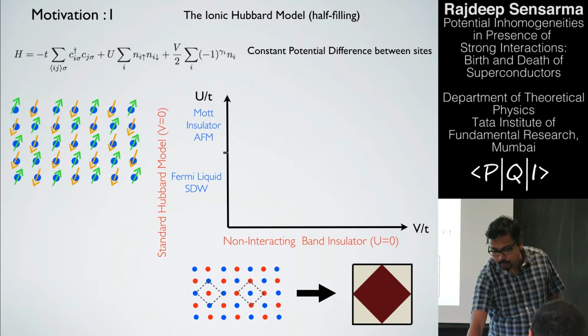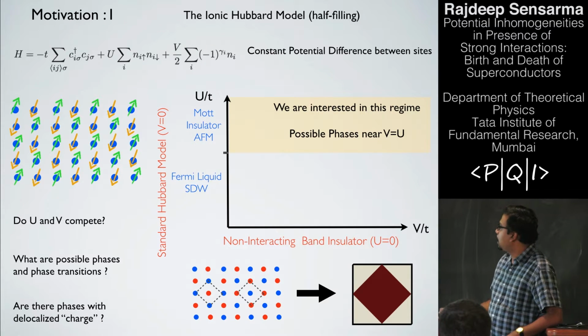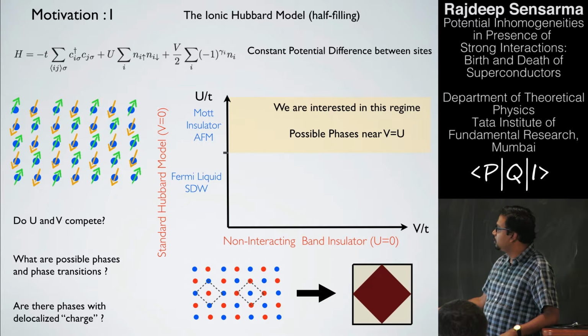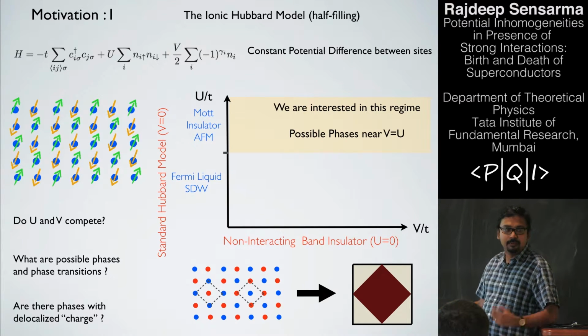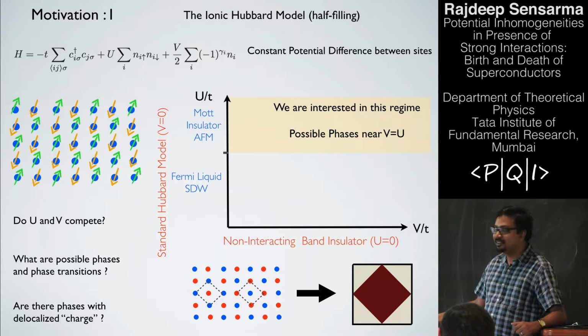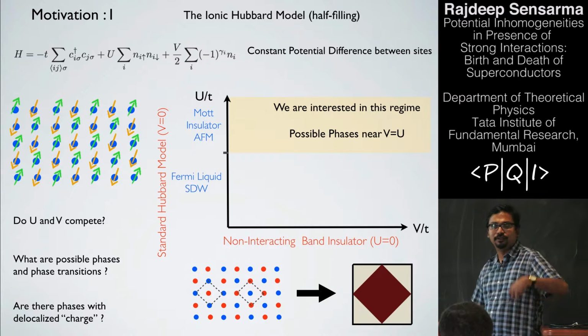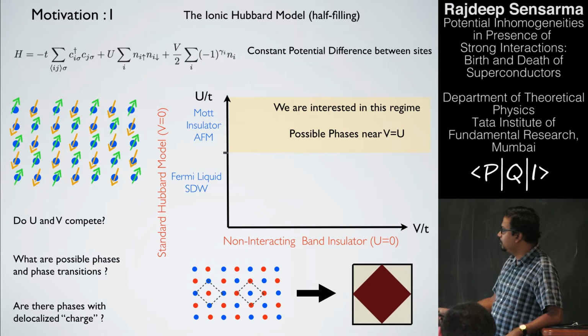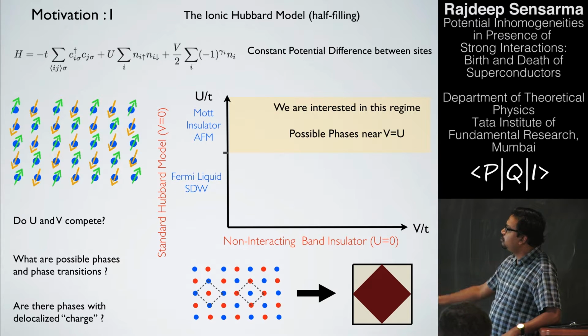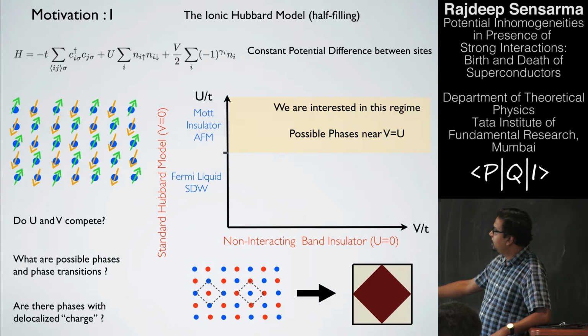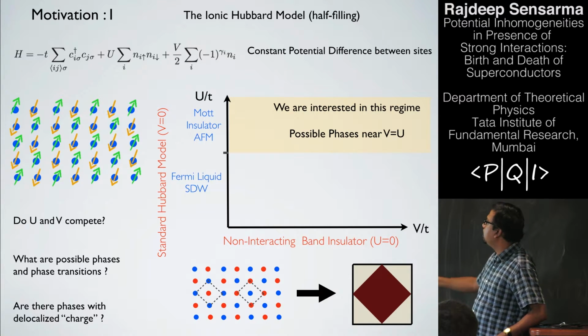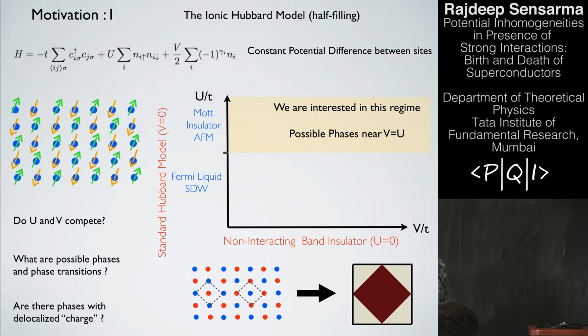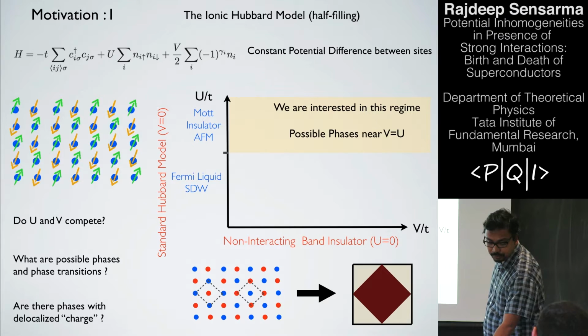Before that, what are we looking at? We are looking at this model where if I set U, the interaction, equal to 0 and I look at V, as I have said, I have broken the unit cell symmetry, so it will remain a band insulator. This is a Slater, in this case not spontaneously broken symmetry but a superlattice potential, but this will give you a non-interacting band insulator. If you set V equal to 0 and go up in U, you get a Fermi liquid or a spin density wave, depending on exactly where you are, and then as you crank up U, at some point you go to this Mott insulating regime. And what we are going to look at, in this regime, are possible phases near V equal to U, and see what happens to the system.